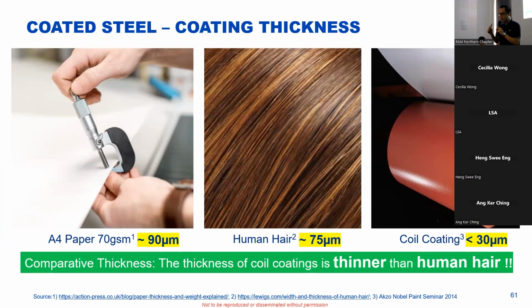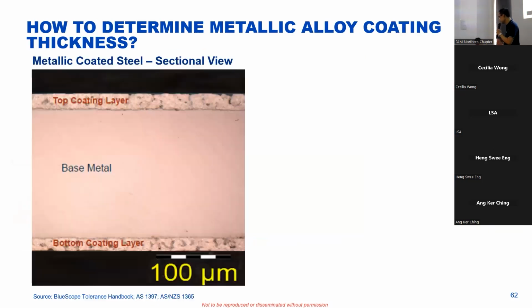If we don't do it properly, failure can happen easily, because the layer is so thin. Let's say the sheet goes to the site, and the installer doesn't carefully handle the product, and there is a big stretch, for example, then the product will of course fail massively. This coating layer is very key.